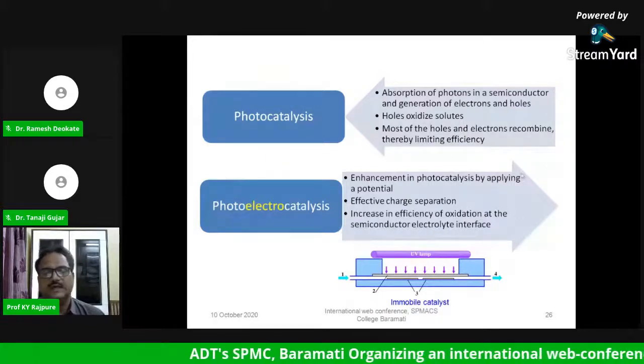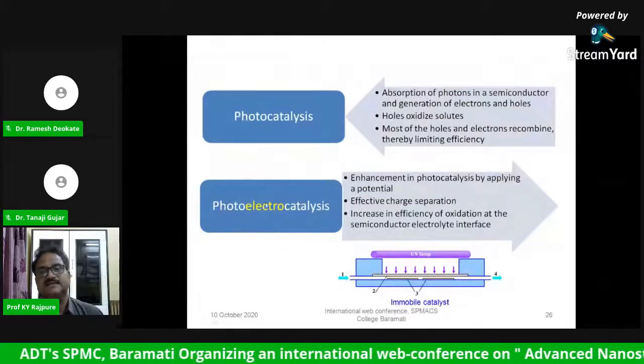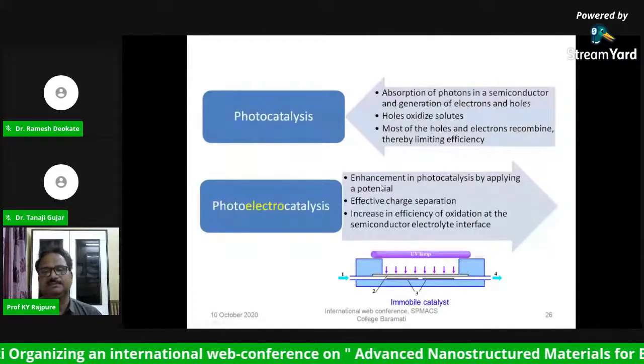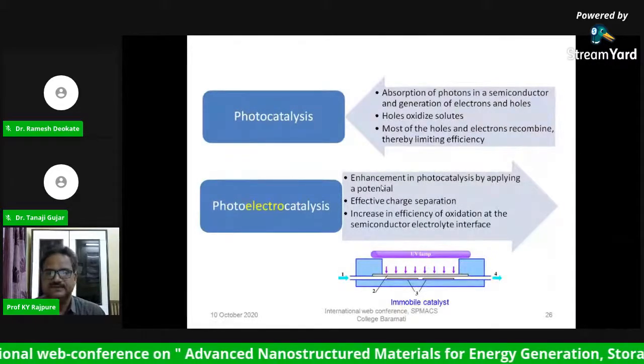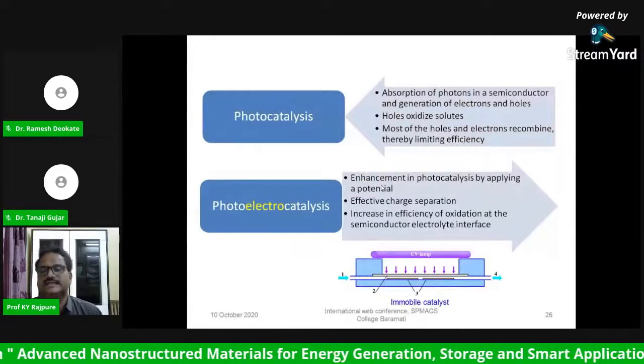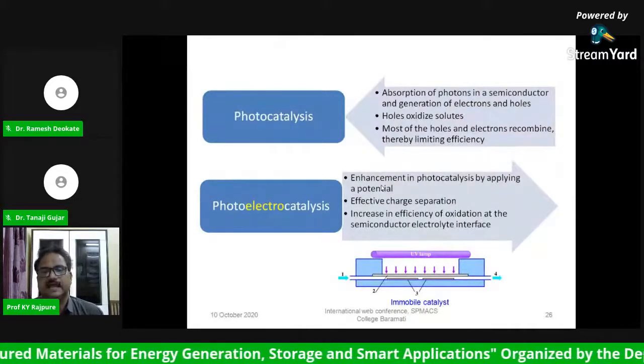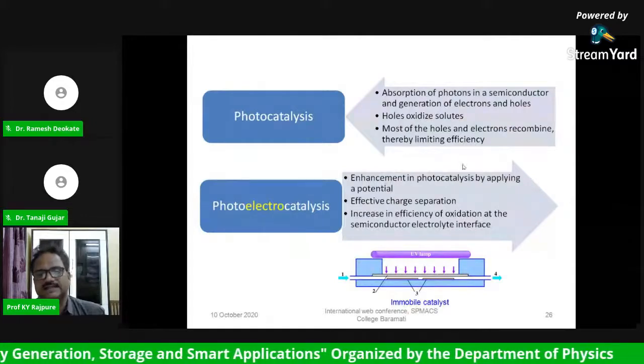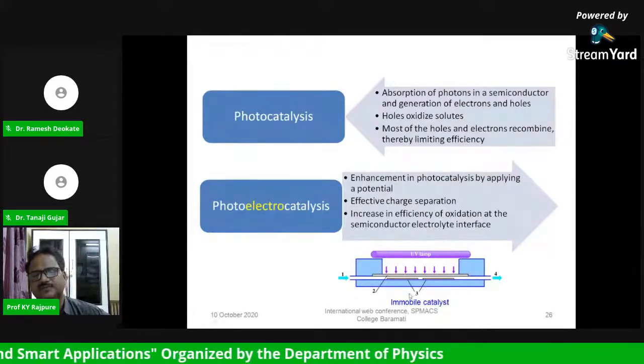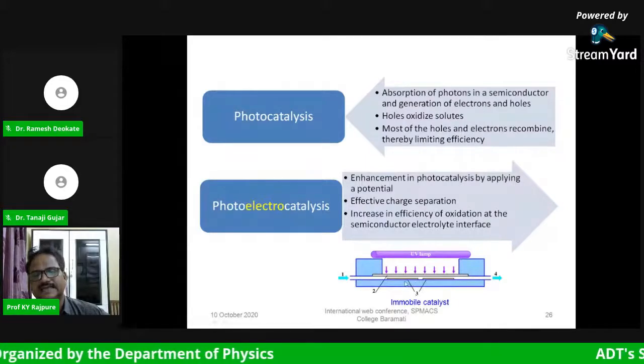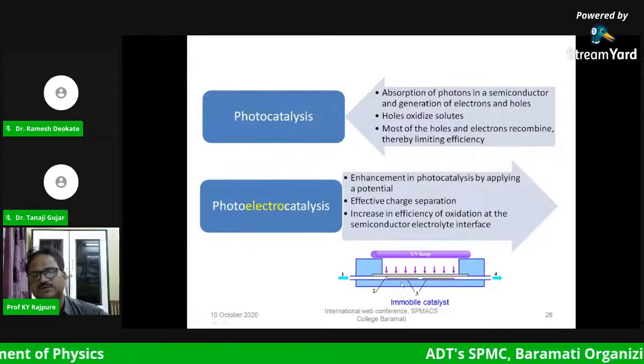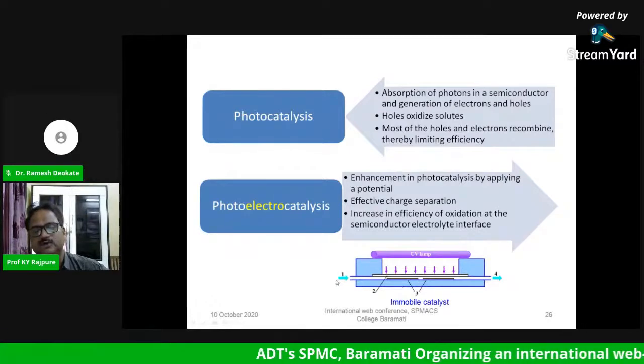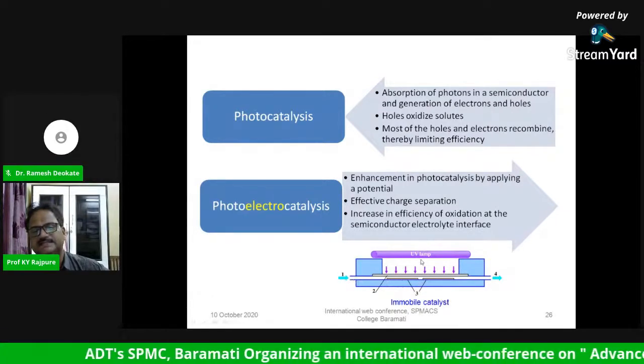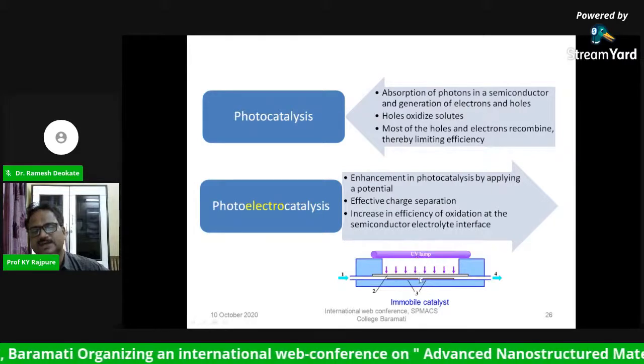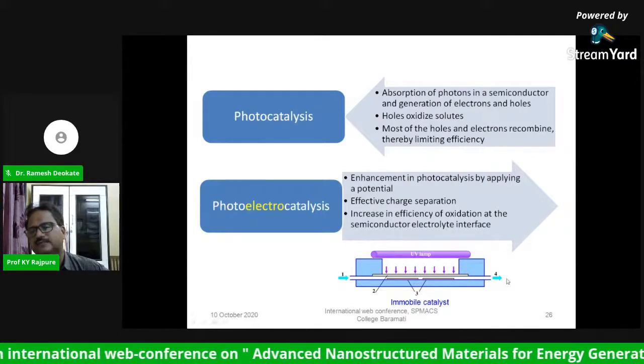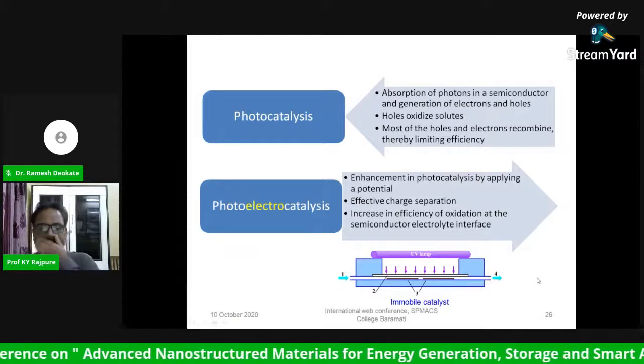So what happens if we apply electrical bias? We can enhance the photocatalysis by applying the bias, because there is effective charge separation. The recombination between electron and hole can be reduced to a greater extent, and we can increase the efficiency of the oxidation. And this is a small schematic diagram of the immobile catalyst, where the catalyst is in the form of a thin film on the substrate, and the impure water is purged in from here, and there is a provision to illuminate this junction between impure water and photocatalyst, and the purified water comes from the other end.